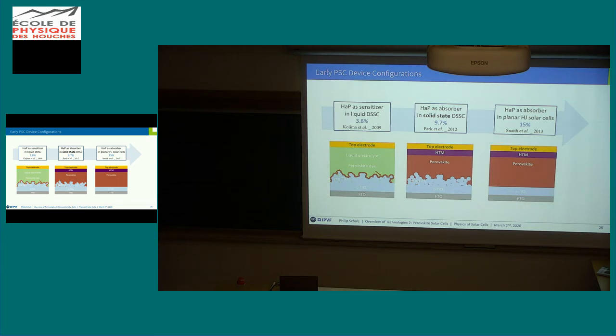So we start with the early perovskite device configurations, and I said it already. It comes from the dye-sensitized solar cell, and the perovskite itself was conceptualized as a dye for the DSSC, and thus it was used with this liquid electrolyte, where the dye was around the mesoporous titanium oxide nanoparticles. It was actually the issue that this configuration was extremely unstable, only lasted for a few minutes before the perovskites dissociated, and you could only measure in this short time a power conversion efficiency of 3.8%.